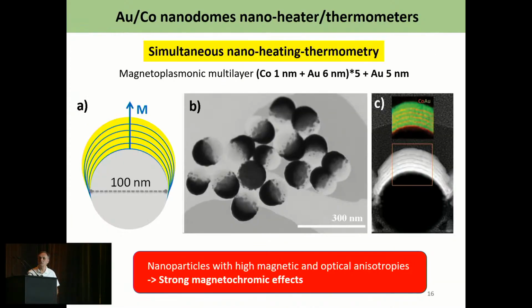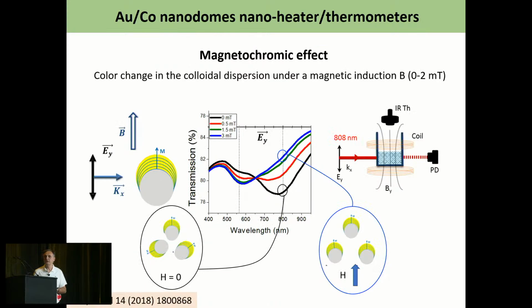So what we did, we designed a new type of nanoparticles. This time, instead of having iron and gold, we made a multilayer of cobalt and gold. These nanoparticles have an in-plane magnetization and have a much stronger magnetic anisotropy than our previous nanodomes. Then we measured the transmission of these nanoparticles. We put them in suspension, shine light, and measure how much light goes through. But now in this case, we have a magnet in our system.